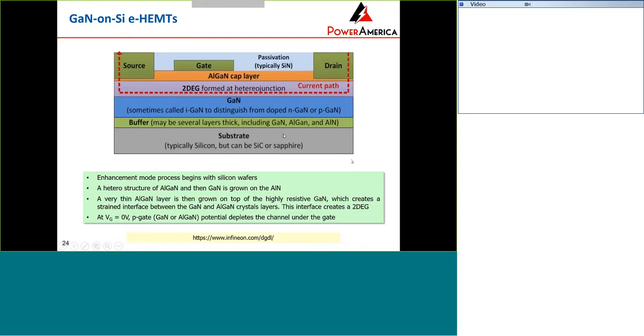This simplified cross-section shows the gallium nitride devices. They grow the gallium nitride in multiple layers on a silicon substrate, and the 2D gas is formed between the AlGaN and the GaN layers, with source and drain on the surface. For the gate, they could use Schottky, or a P-type AlGaN layer, or both, to achieve the normally-off feature of the gallium nitride devices.